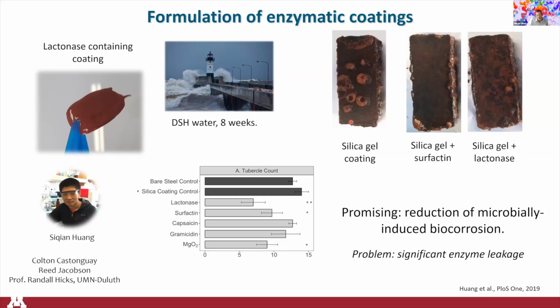And so what we look at here is microbially induced corrosion, because one of the things that some microbes can do also when they grow is to accelerate the process of corrosion because of their metabolisms. There are several ways they can do that. I'm not going to dive into the details of that. But we observed here, as you can see, that there is a lot more corrosion in the coating alone than in the coating plus the biocide. And the coating plus the enzyme has the least amount of corrosion. So this was very promising.